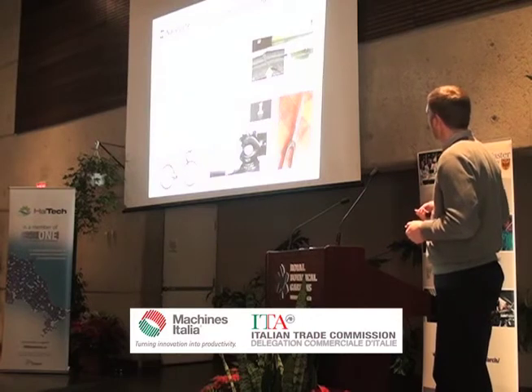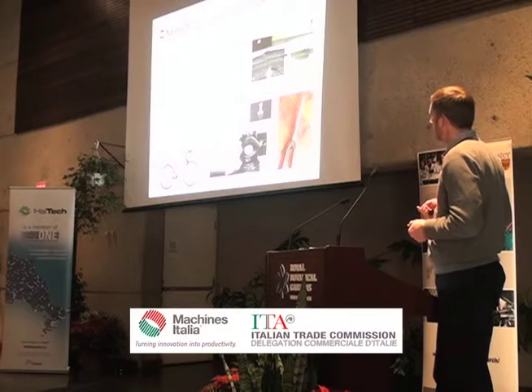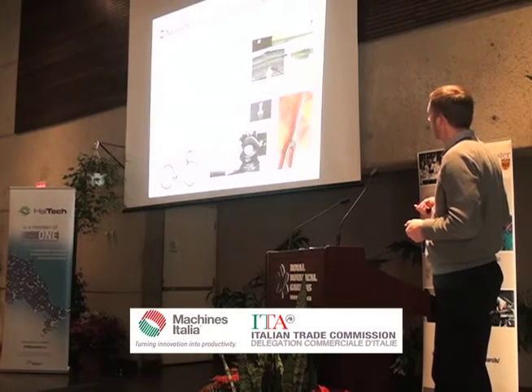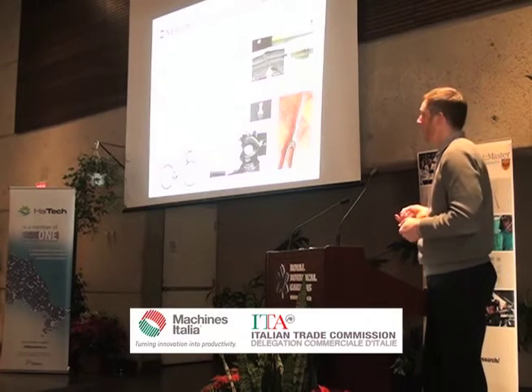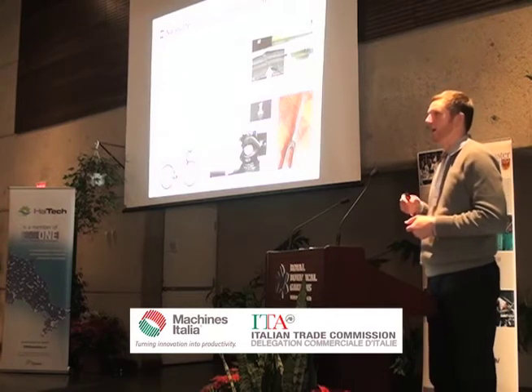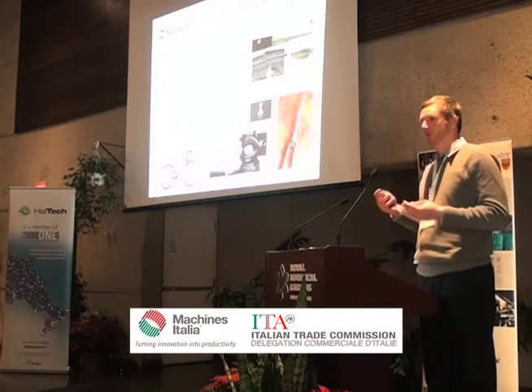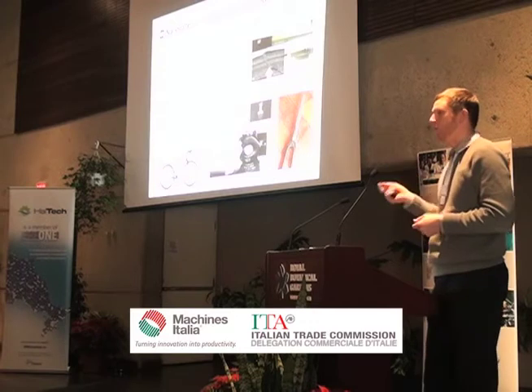So this more or less goes over what I was talking about here, but to give you a specific example, the composite bike fork added with 50 microns of Nanovate gave you a 20 times increase in the fatigue life. That's fairly important. But what made this special is something else that Integran has designed and invented essentially, this Integran material, which enables a good level of adhesion between the composite and the Nanovate metal.